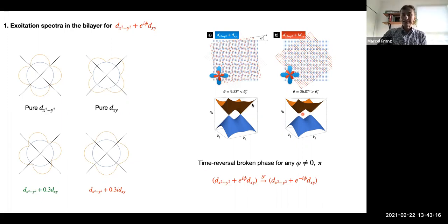Now, high Tc cuprates are an exception to this rule. In their native state, they are actually gapless. And that's this picture here, that the size of the gap on the Fermi surface actually has this D-wave structure, and it vanishes at 4 points.